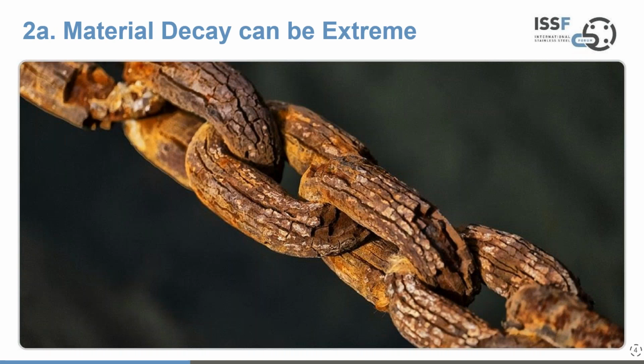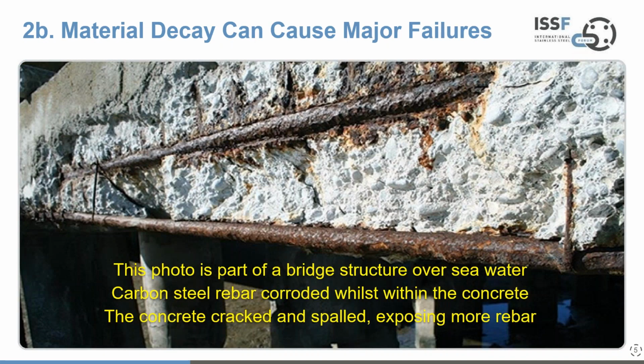Because material decay can be quite extreme, as shown in this picture of a steel chain. And material decay can cause major failures. This is an example of a part of a bridge structure over seawater. And it's constructed very traditionally with carbon steel rebar, concrete encasing that. And the carbon steel rebar is corroded whilst within the concrete. Because that's a volume expansion, rust is bigger than the volume of the original substrate metal. The concrete cracks, spalls, and exposes more rebar.